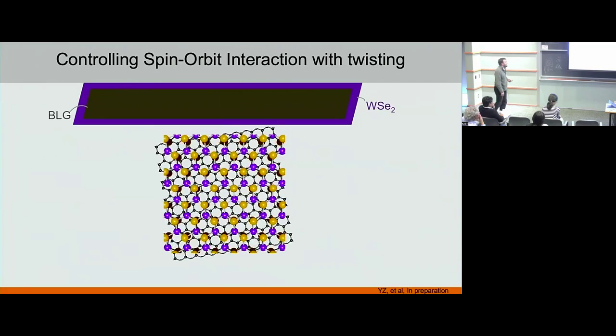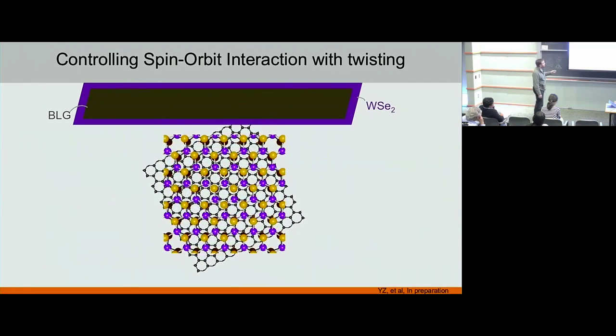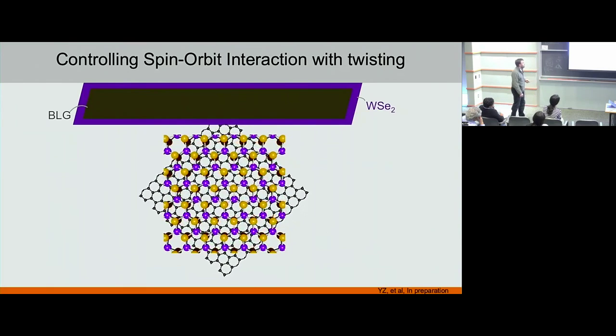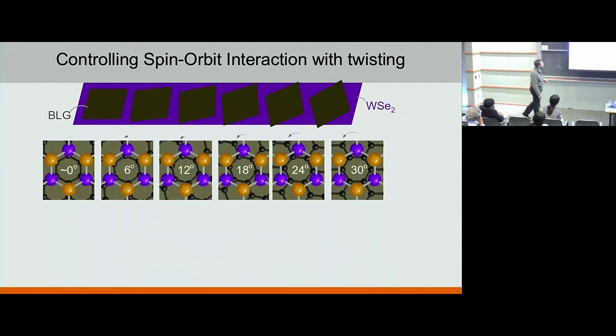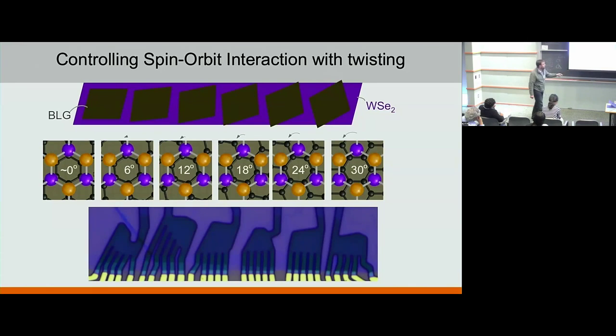So now the main question is how do you rotate? It's not super easy to rotate in situ, but you can make a bunch of samples, each of them slightly offset. You start with a big flake of graphene or bilayer graphene, and a big flake of tungsten selenide. You cut your graphene flake, then you use your tungsten selenide to pick them all up, and each time you pick them up, you rotate it slightly. Then you get a range of samples with different angles. And this is how they actually look. They all have multiple contacts, and now you can measure all kinds of things.